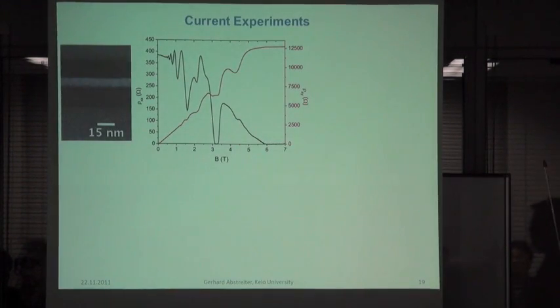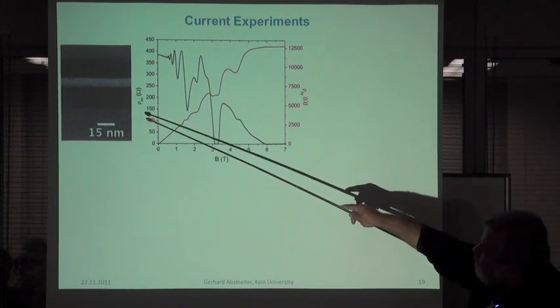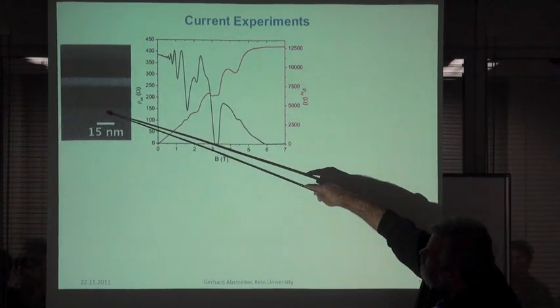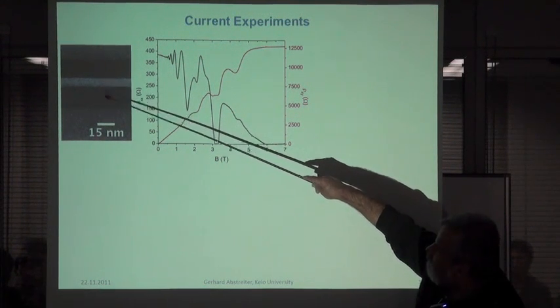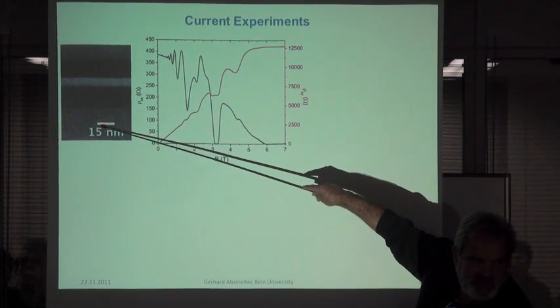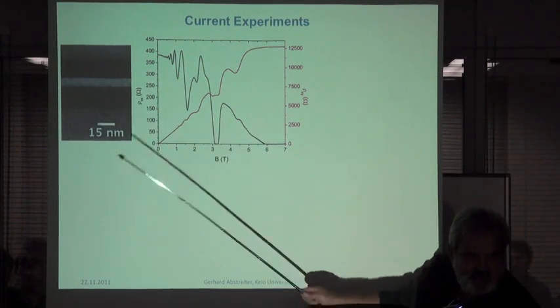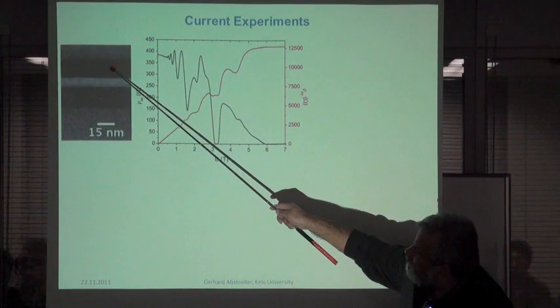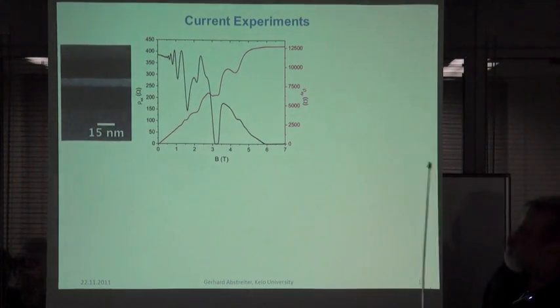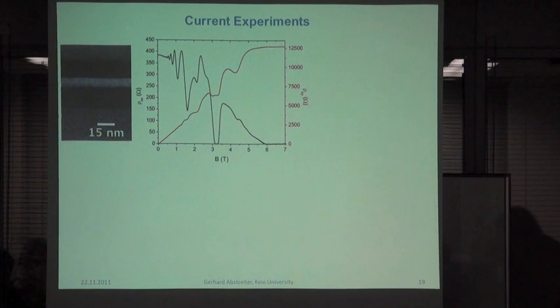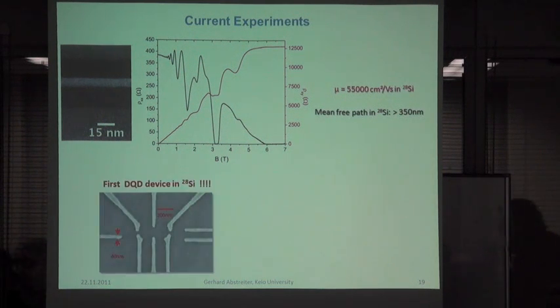And so this is actually one of the structures. This is the isotope clean part here. This is a silicon channel. And we could not adjust the concentration perfectly from the natural to the isotope clean because we use these different sources. And so we had to have different germanium concentration here than in the relaxed buffer layer. But nevertheless, we get quite high mobility. And the mean free path is then more than 350.